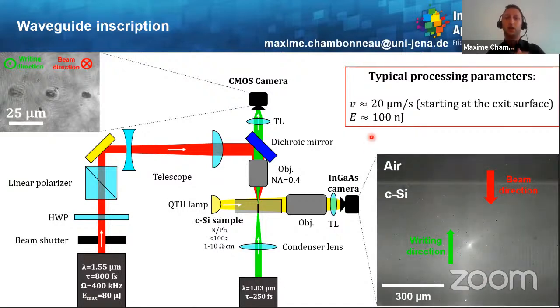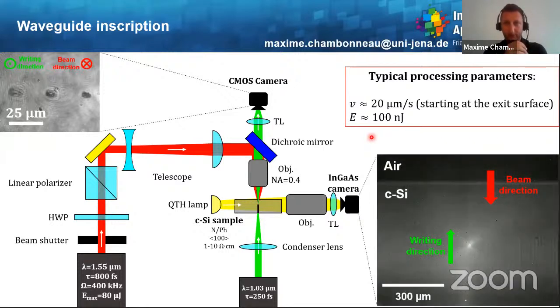So what is the trick we have found for inscribing waveguides inside silicon? Well, we start by damaging the exit surface of the sample, so creating a crater on the exit surface of the material, and then move upstream towards the laser at a constant speed. Here, typically it's 20 micron per second and on the order of 100 nanojoules for input pulse energy. And then you can propagate and extend this crater, but you produce some strain and permanent modification inside the material by doing so.